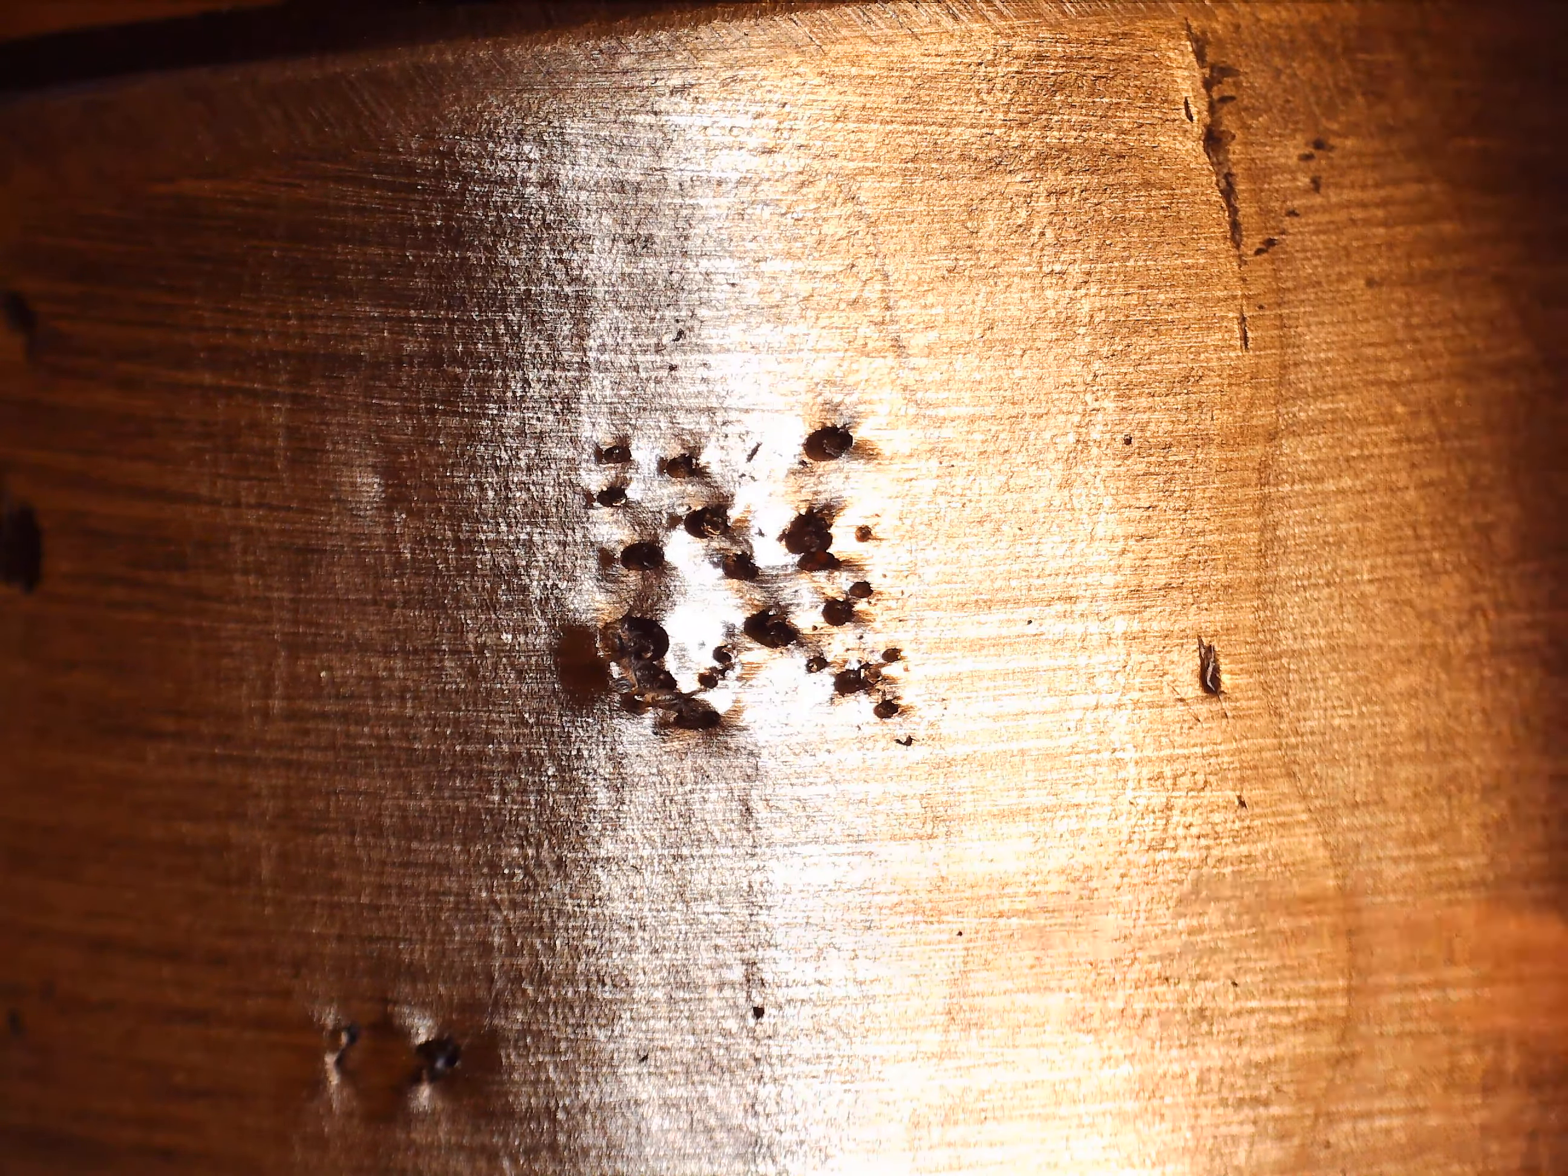Here these are all joined, and I would estimate this at three thirty-seconds. Some might say it's closer to 1/8 inch, and it very well may be. It's not quite an eighth though. Let's just call it an eighth, okay, just for the sake of wanting to reject this as well, because we're the inspector. So we'll add the eighth in right there.